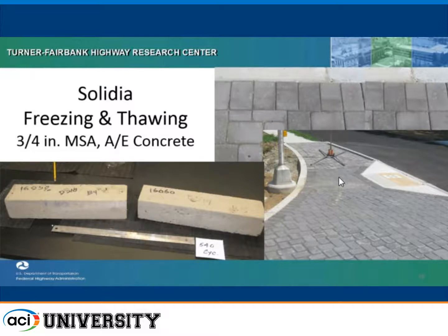With Solidia, we recently completed some freezing and thawing tests, again with our 3/4 inch maximum size aggregate air-entrained concrete. I think that was 540 cycles of freezing and thawing. And in general, the material's holding up very well. We're getting a little bit of scaling, which is not a surprise. We also were doing some intersections and sidewalk work at Turner-Fairbank Highway Research Center, and some of the Solidia paver block were used in part of that sidewalk. So we're trying to get the material out there and see how it performs in actual practice.